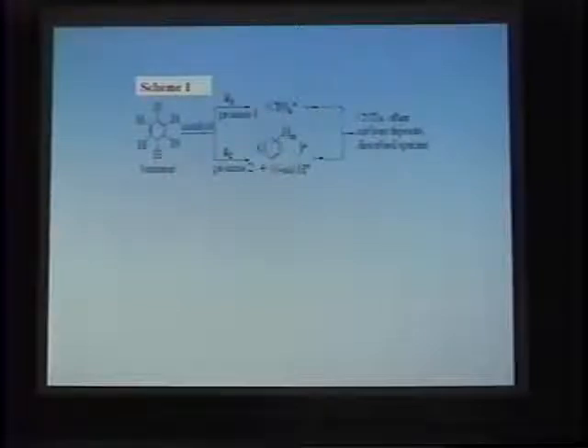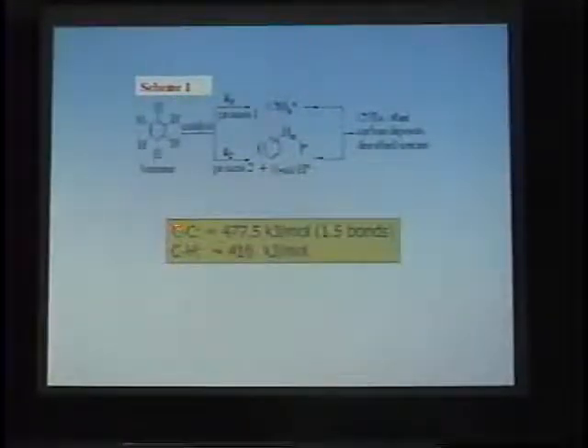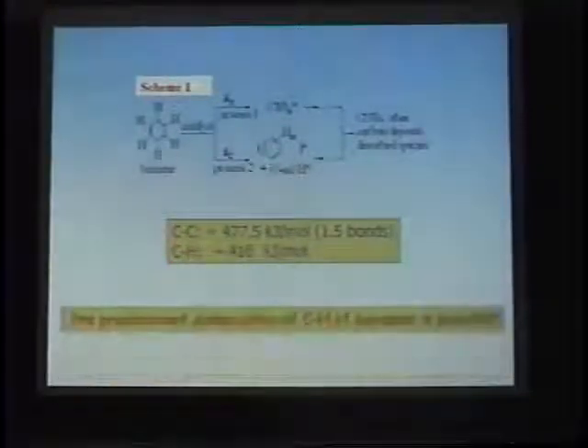As we know, the carbon-6 ring of benzene is very stable. The bonding energy of the carbon-carbon bond is 477.5 kJ per mole, and the carbon-hydrogen bond has a bonding energy of 416 kJ per mole. So the carbon-hydrogen bond is weaker than the carbon-carbon bond, so it's possible to dissociate.